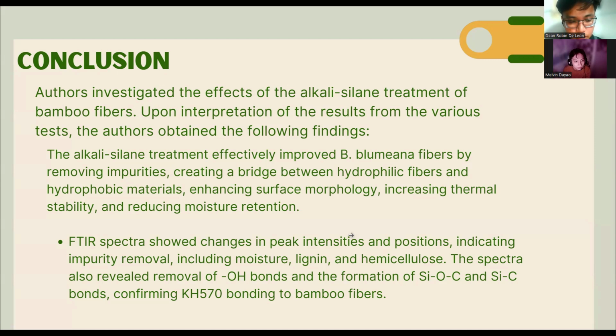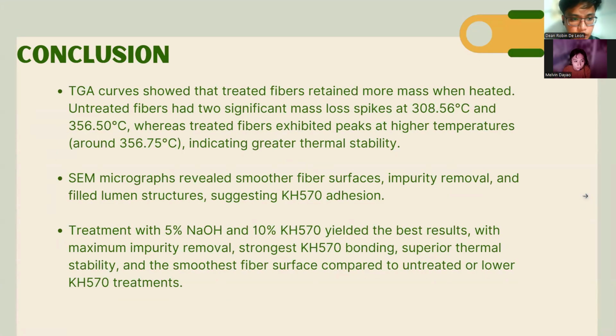The FTIR spectra showed changes in peak intensities and positions indicating impurity removal, including moisture, lignin, and hemicellulose. The spectra also revealed the removal of OH bonds and the formation of Si-O-C bonds and Si-C bonds, confirming KH570 bonding to bamboo fibers. TGA curves show that the treated fibers retained more mass when heated. Untreated fibers had two significant mass loss spikes at 308.56 degrees and 356.50 degrees Celsius, whereas treated fibers exhibited peaks at higher temperatures, at around 356.75 degrees Celsius, indicating greater thermal stability.